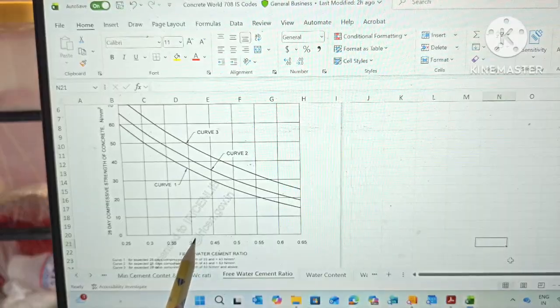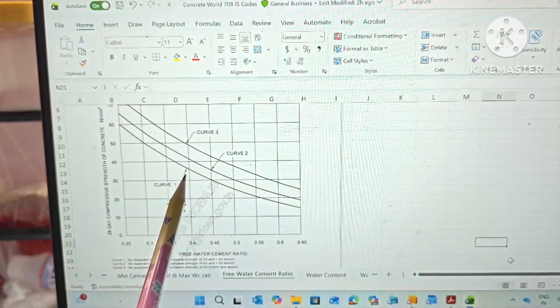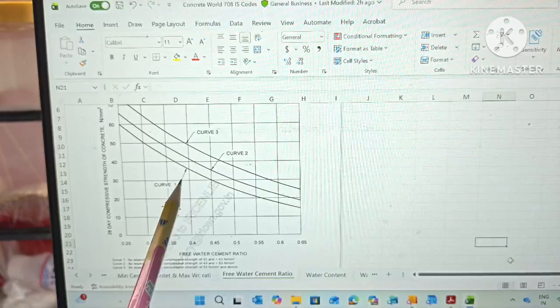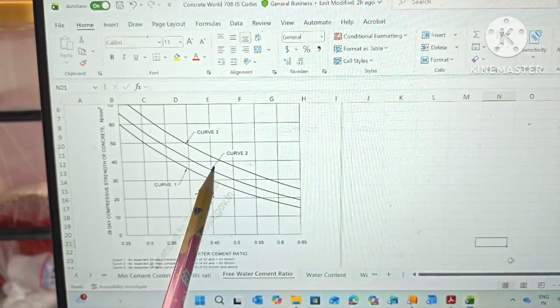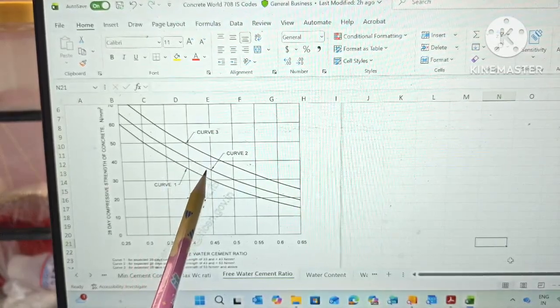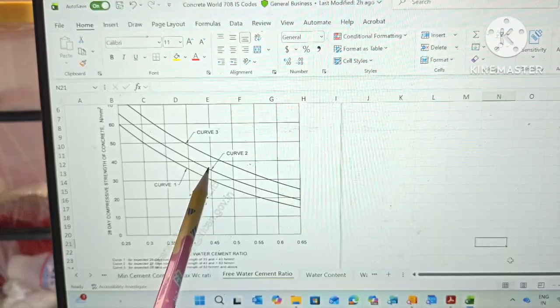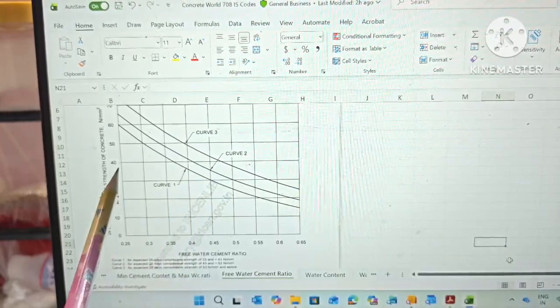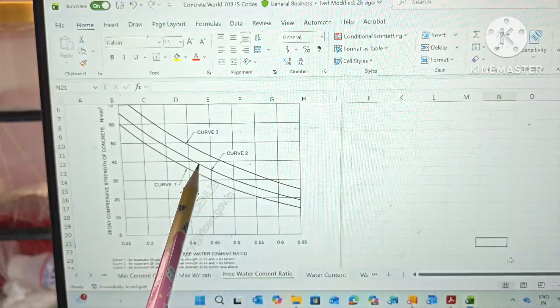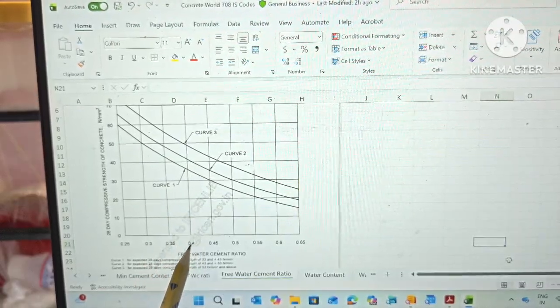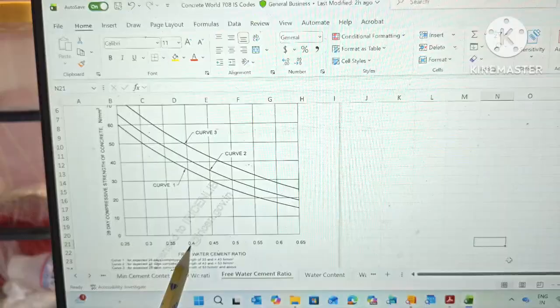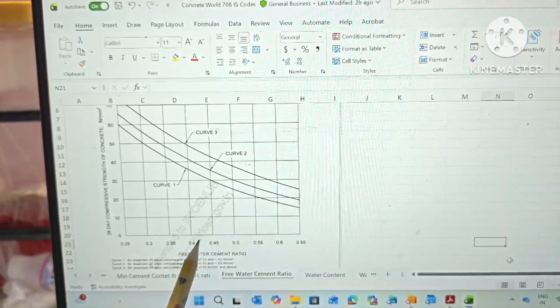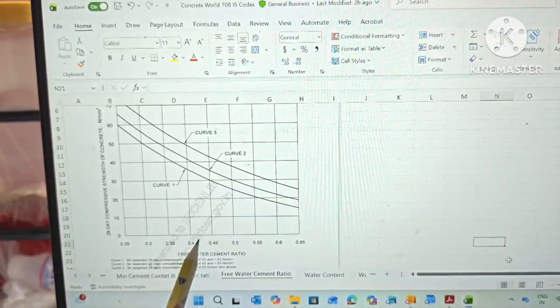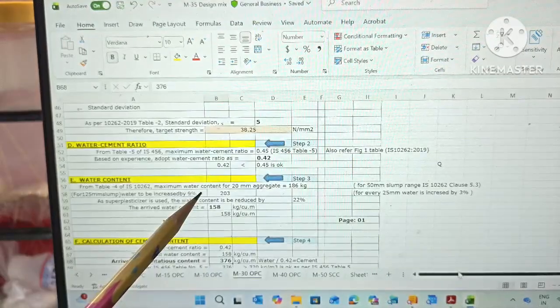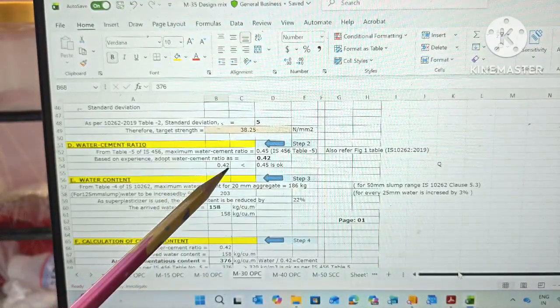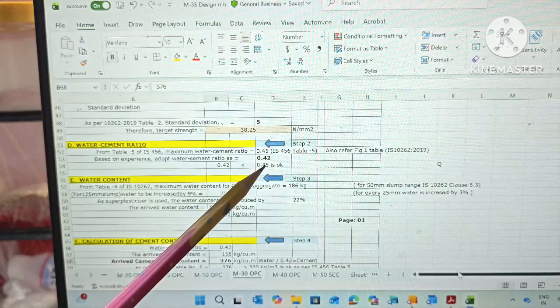Now your question is, why do we take curve 2 and why not curve 1 and why not curve 3? Friends, curve 1 is for 33 grade, curve 2 is for 43 grade, and curve 3 is for 53 grade. We are using OPC 43 grade, that's why we deal with curve 2. So 38 intersects curve 2 here, and when we go down we can see that our water cement ratio lies between 0.4 and 0.45, that is 0.42. So we'll consider a water cement ratio of 0.42, and since 0.42 is less than 0.45, it is okay.